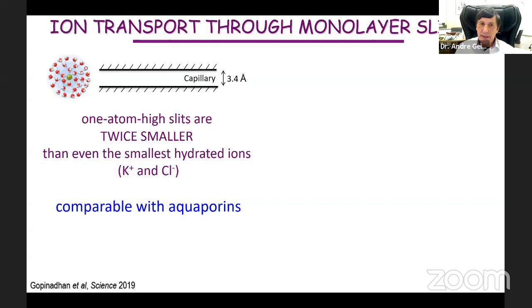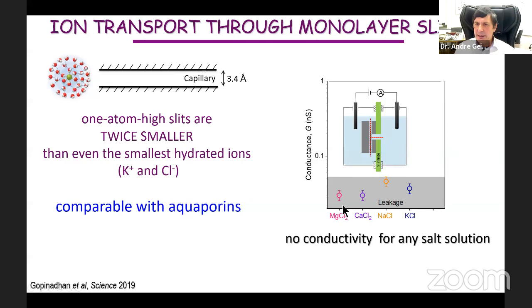So we know that water goes through. The question is whether other ions, even the smallest ones, can go through. And whatever salt we tried, in this case there are only 4 salts, but we tried many other salts as well, we don't see any conductance at all. The channels allow water, but no noticeable conductivity for ions in this case.